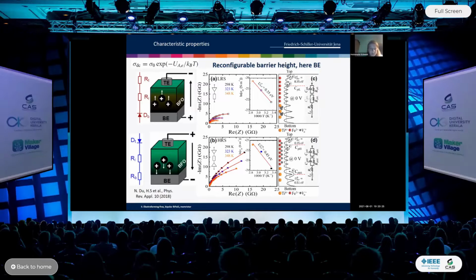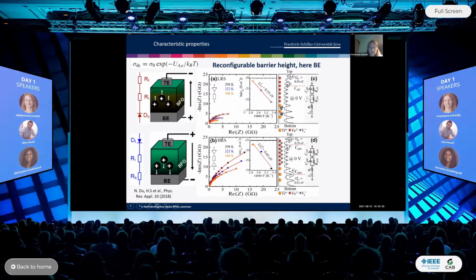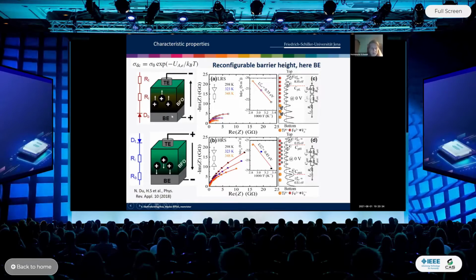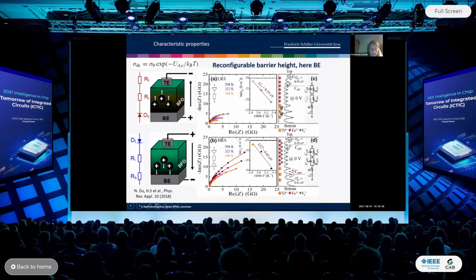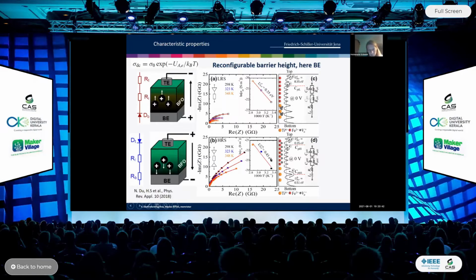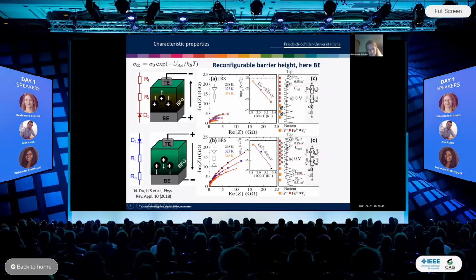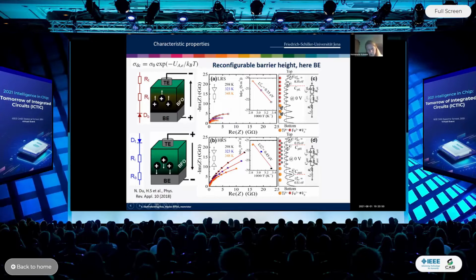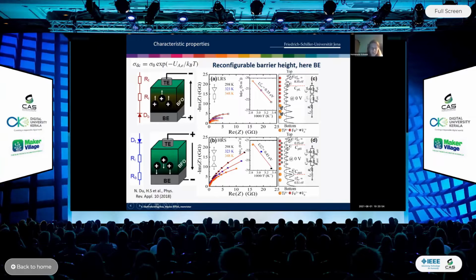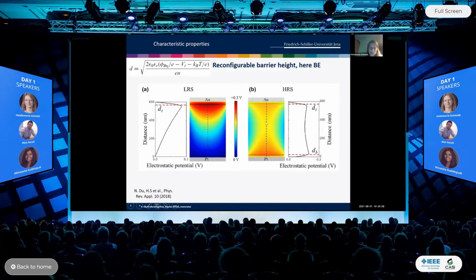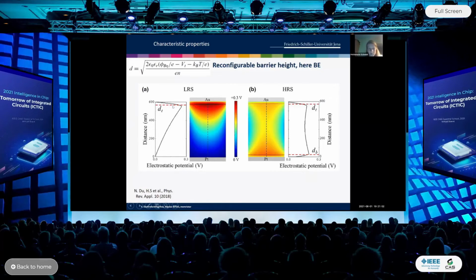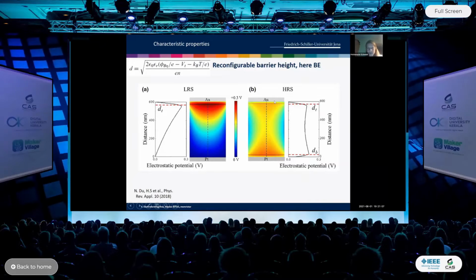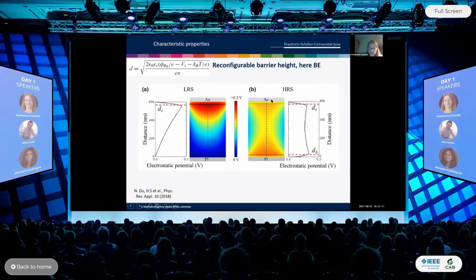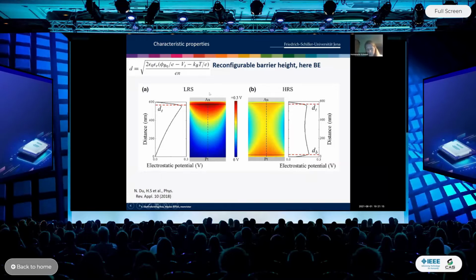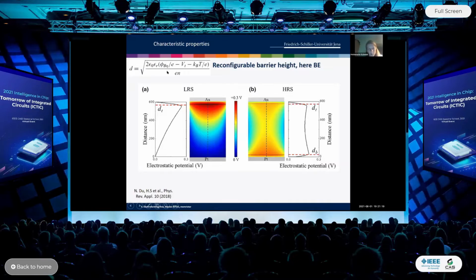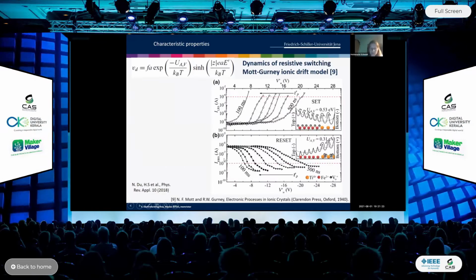The barrier height we could easily determine using impedance measurements. After having put the system into the low resistance state or into the high resistance state, we determined the barrier height of the top electrode and of the bottom electrode using impedance measurements. And here you see the barrier height is 0.35 electron volt for the top electrode, and for top electrode plus bottom electrode it is 0.43 electron volt. And then one can also make a simulation using COMSOL in that case. What is the extension of the depletion layer in the low resistance state and in the high resistance state? We have a depletion layer below the top electrode and above the bottom electrode. And one can calculate how large the extension of the depletion layer is depending on the barrier height of the top and of the bottom electrode.